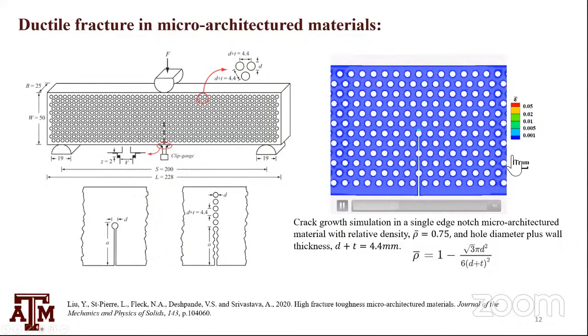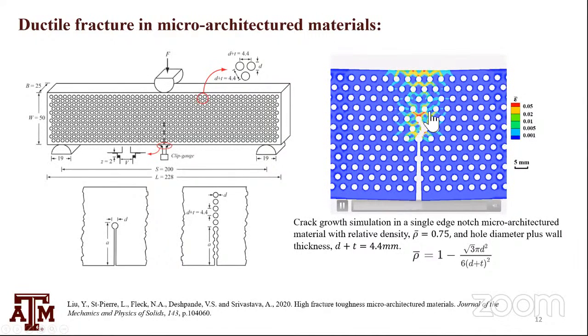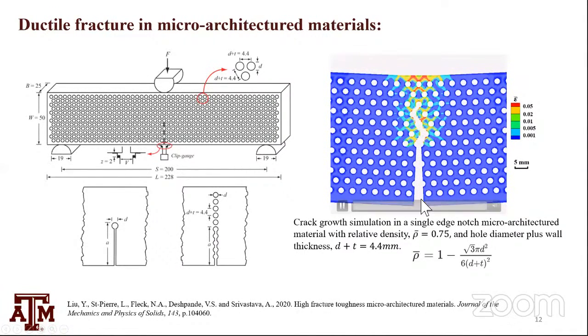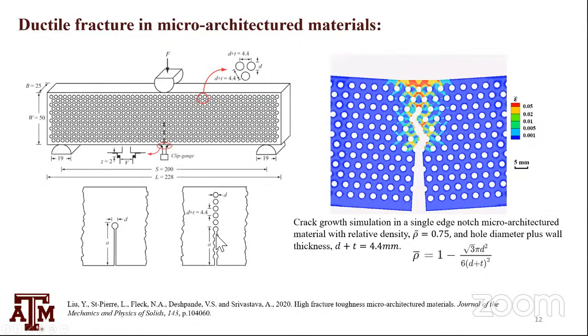Easily we can model these voids discretely and let the crack propagate, and we can then plot these values with respect to the hole diameter and spacing, in a single row of holes and in this hexagonal array of holes, which is the microarchitecture material, and look at its fracture toughness.